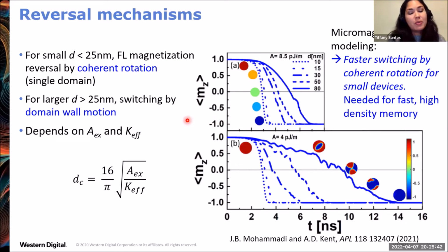Okay. Now, if the free layer size or your bit size is larger than 25 nanometers, the flipping will happen by domain wall nucleation and propagation. And you can see this on the right side here, I'm showing a micromagnetic modeling study of these reversal mechanisms. And so this one shows domain wall motion for reversal of larger bits. Here you can see that it's nucleated in the center, and the domain wall propagates outwards to be completely flipped. And you can see that that process, domain wall motion, takes longer compared to coherent rotation. And especially it takes longer if the exchange stiffness of your free layer material is small. So you can see here that we will get faster switching by using small devices that are in this coherent rotation regime. And this is what would be needed for a fast and high density memory.